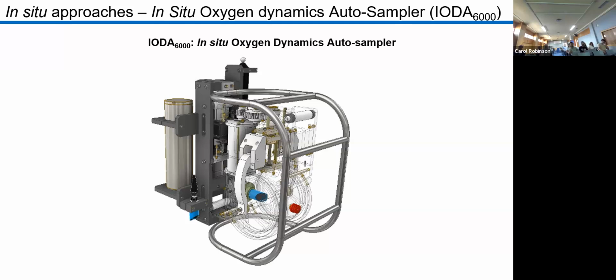So if you consume a micromole of oxygen, like bacterial respiration, the plastic gives it back, so you can't measure anything. Wrong material to use in an in situ incubator. You can try to precondition the plastic, but it takes more than 6 months.